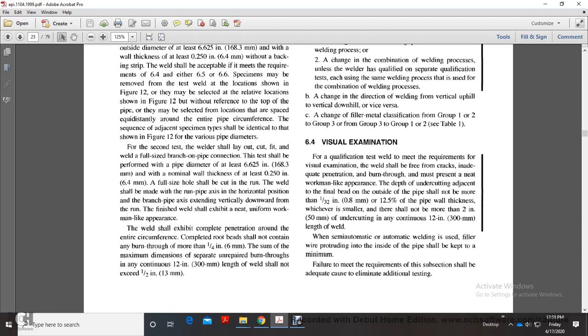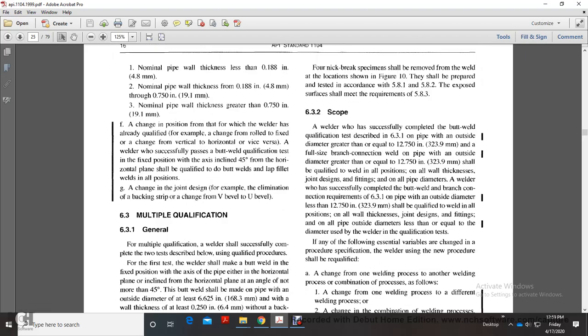The finished weld shall exhibit a neat, uniform, workman-like appearance. The weld should exhibit complete penetration around the entire circumference of the completed root bead. It shall not contain any burn through of more than a quarter inch. The sum of the maximum dimensions of separate unrepaired burn-throughs in any continuous 12-inch length of the weld shall not exceed 1/2 inch.